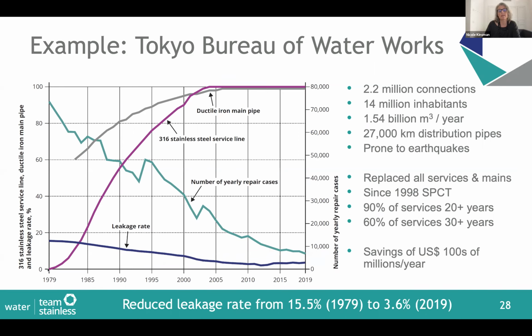And in the late 70s, the leakage rate already wasn't so bad at 15, 16, 17%, but they were growing strongly in Tokyo. The city was growing, and they were worried that they wouldn't have enough water for everybody. So they started to look where to save, and leakage was one of the solutions. So they came up with a program that wasn't only the replacement of services, but they replaced all services and mains. So that was over 25 years or so. You can see here how they have replaced all service lines with stainless steel, and they arrived at 100% here around 2003 or 4. Also, the mains have been replaced with ductile iron mains, and many of them seismic resistant ductile iron mains.